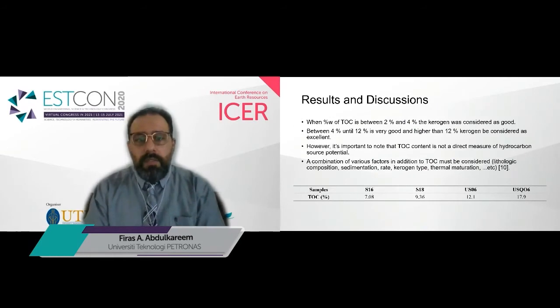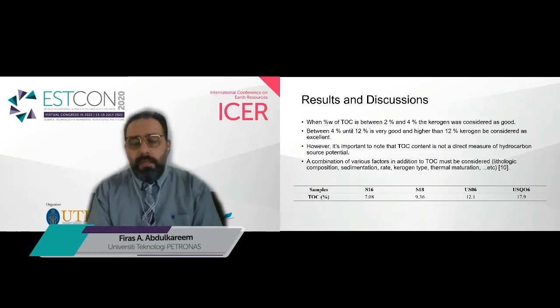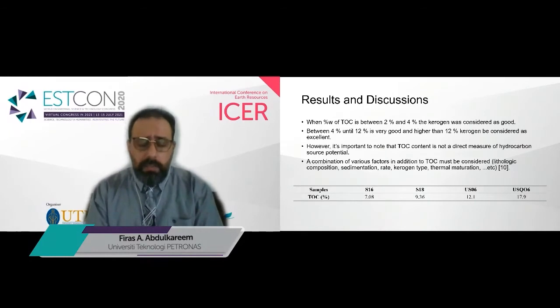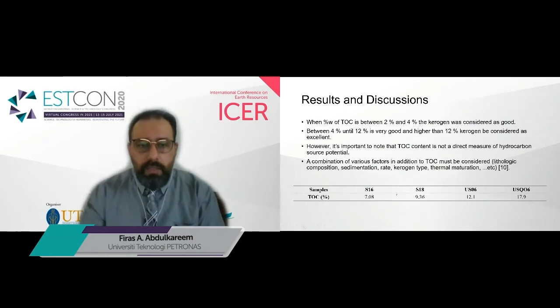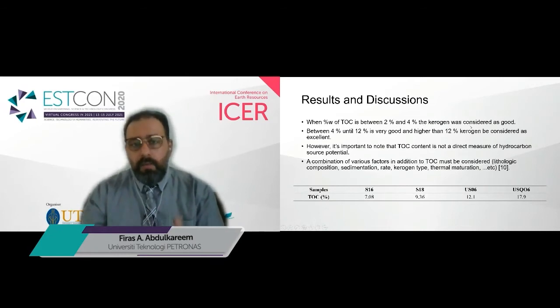In terms of the results and discussion, the first characterization analysis conducted was the total organic content identification of the 4 samples. As we can see here, the 4 shale samples have shown adequate to high total organic content. Actually, from 2 to 4 weight percent of the total organic content of the kerogen was considered a good amount of hydrocarbons to be extracted. Anything beyond 12 is considered very good and high.